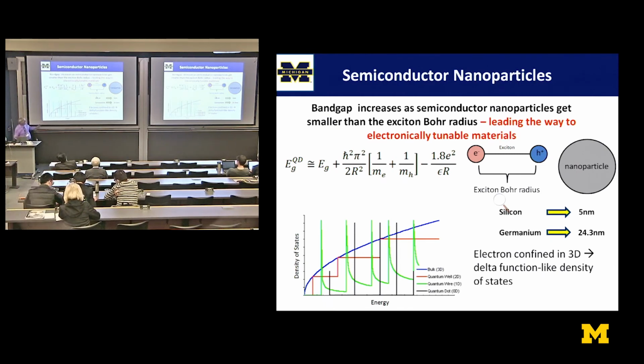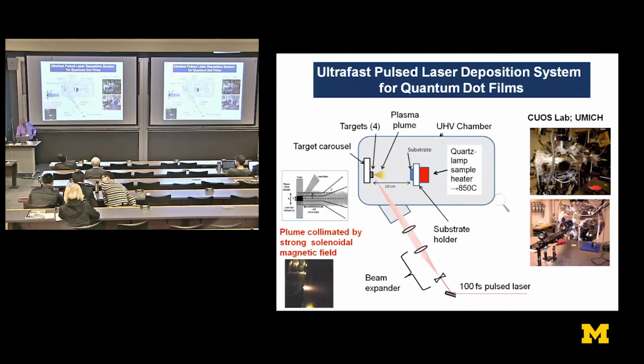The unique singular nature of the density of states has already been described by several workers so far. So we set up a system to deposit films of nanostructures. To my knowledge, this is the first example of an actual film composed entirely of nanostructures. And we did it using, again, a narrow band gap infrared material, germanium,